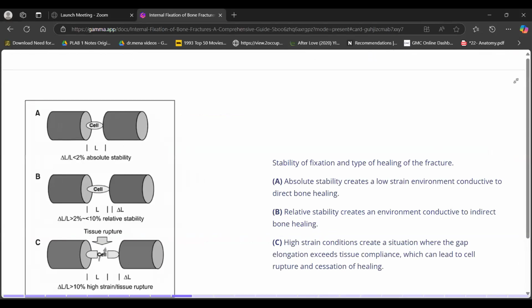So when we are talking about the stability of the fracture or the strain that happens, absolute stability creates a low strain environment conducive to direct bone healing, to achieve primary bone healing. Relative stability causes some strain, I think between 2% to 10%, which can lead to relative stability. And if the strain is more than 10%, this will lead to high gap elongation and less tissue compliance, which can lead to cell rupture and cessation of healing.